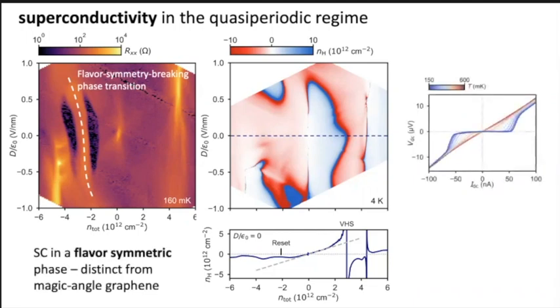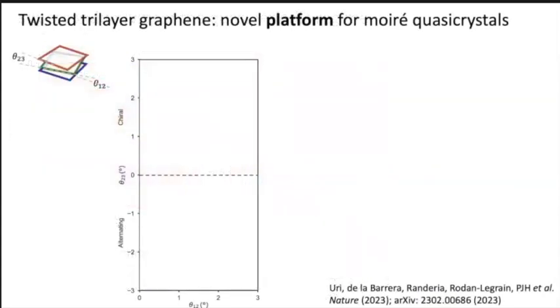So you have superconductivity in this quasi-periodic system, and it happens around where the phase transition happens due to strong interactions, okay? Which is kind of similar to what happens in magic angle twisted bilayer graphene and other systems, though it has a little bit different character. Okay, so this twisted trilayer graphene is a novel platform for Moiré quasi crystals.